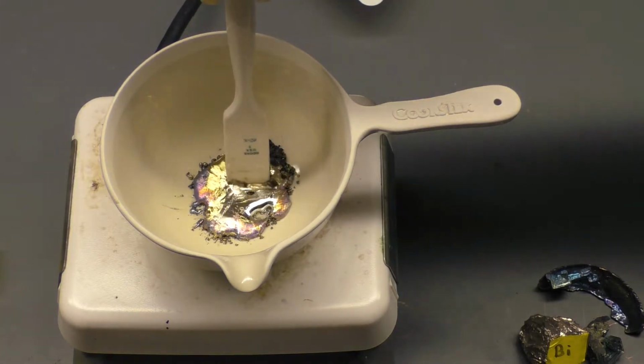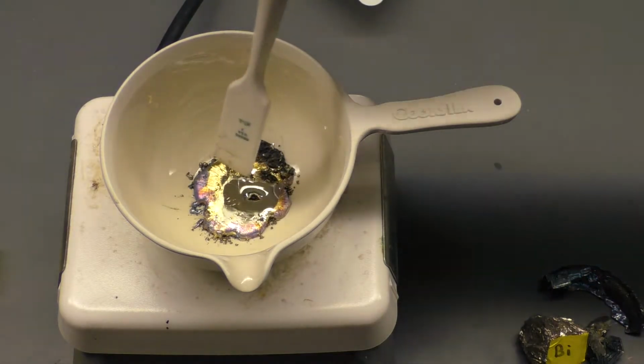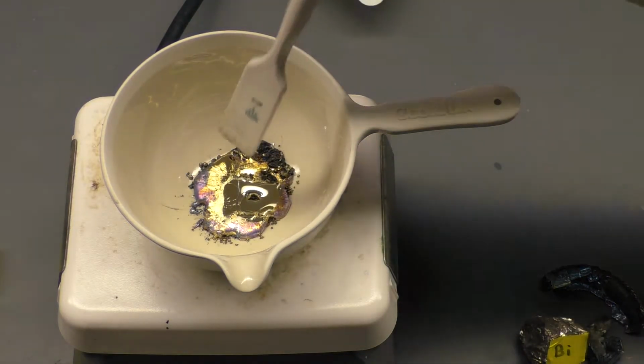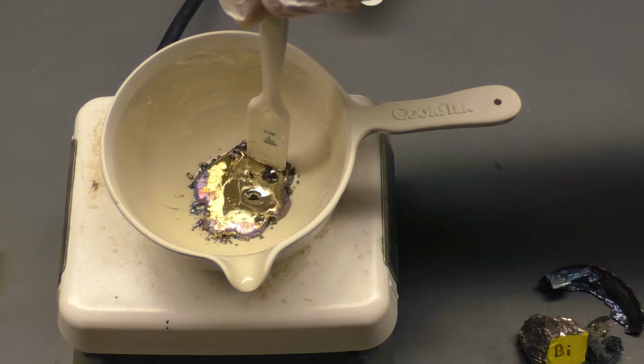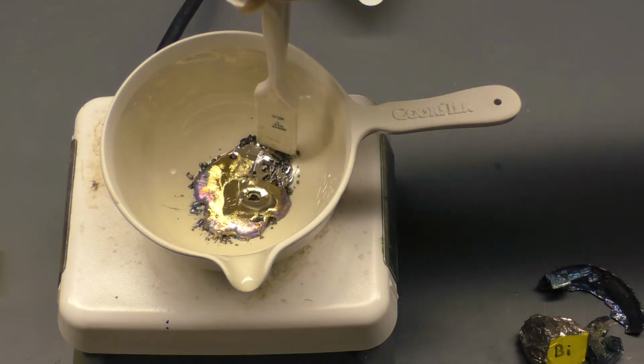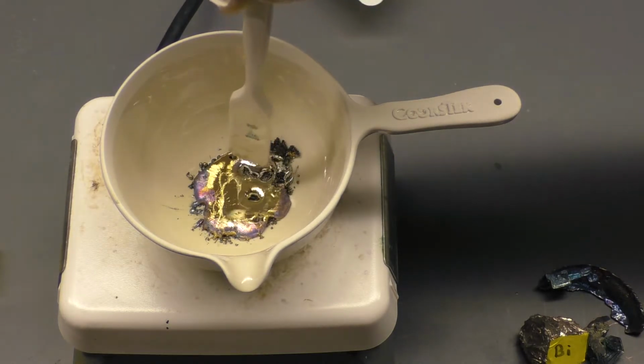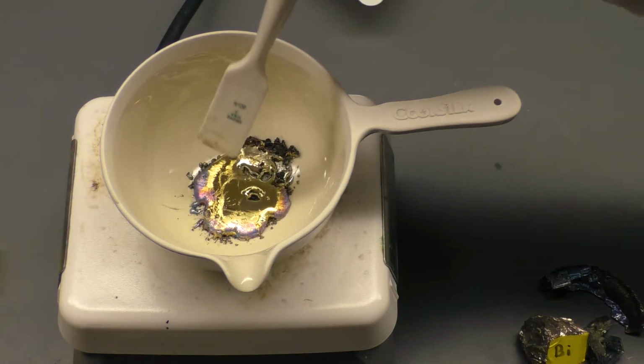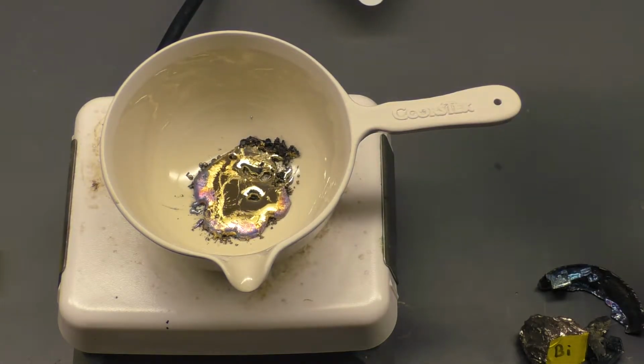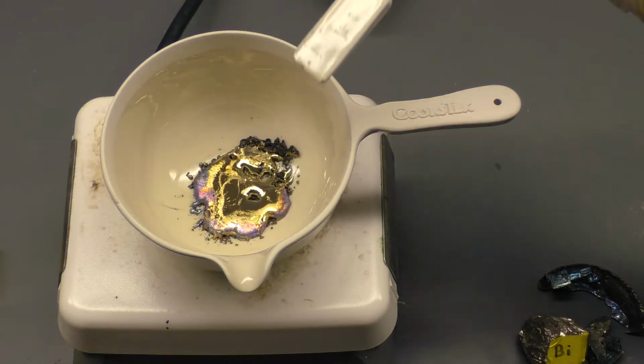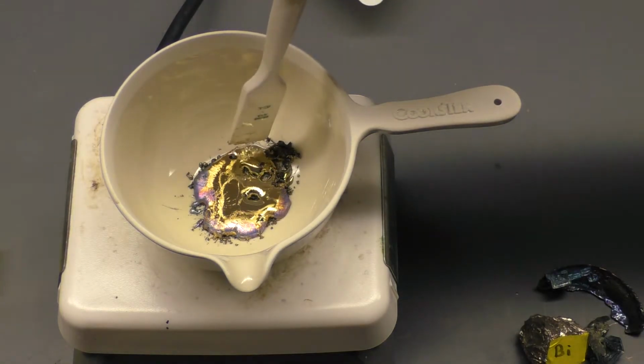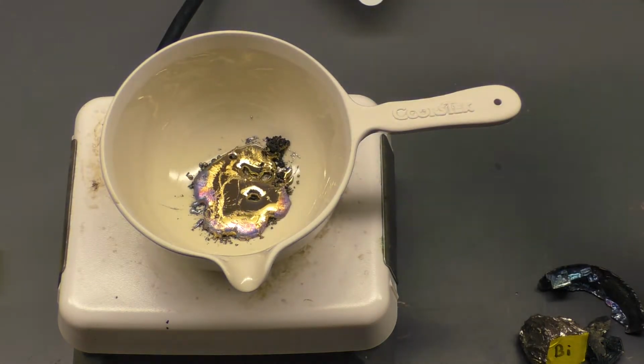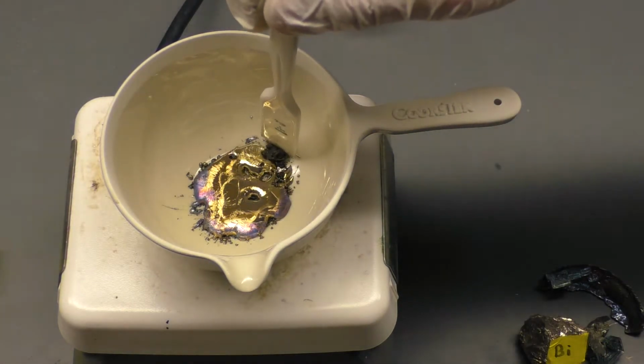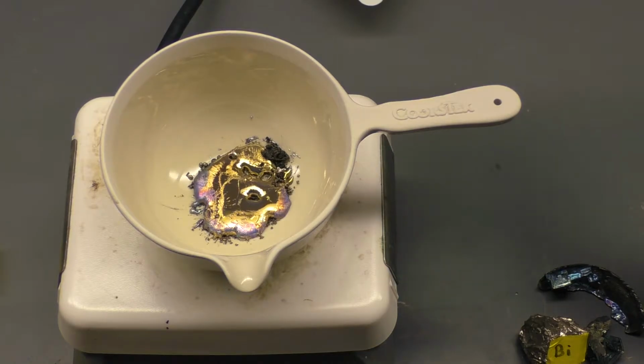And this is actually the molten form of that alloy. Alloy is just a homogeneous mixture of the metals. But actually there's a really cool thing happening. You can see there's kind of this crusty layer on top. That's because we're heating this out in the open air, and the surface of the metal here, which is really hot, is continually oxidizing. It's reacting with oxygen from the air to form an ionic compound called, well, bismuth oxide and tin oxide. And in the metallurgical industry, that's called slag.